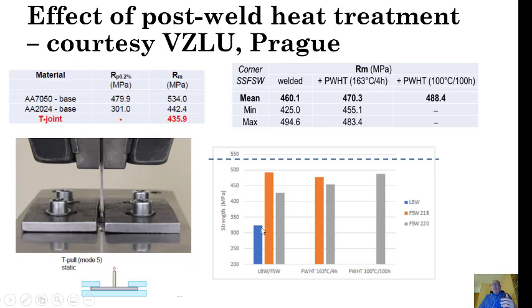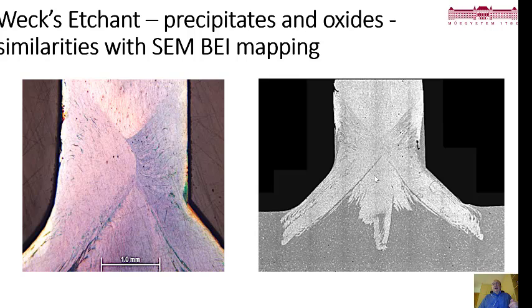Laser welding, by the way, was clearly not a winner, not to call it a loser, but you can see typically fusion welding causes tremendous loss in strength, like TIG welding and others. We know all about that. But you can see that this friction stir weld has tremendous strength and extremely good quality.